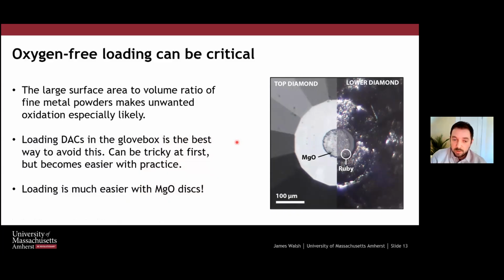The reason this is especially useful for us is if you're dealing with oxygen sensitive materials, such as finely ground metal powders, which can oxidize, and they more readily oxidize when they're fine powder because the surface area to volume ratio is higher. Then if you have to load in a glove box, being able to use magnesium oxide actually makes things a lot more straightforward. We typically will put one piece of the MgO sandwich in the gasket, the other piece on the opposing anvil, and then we close it up in the glove box after having dropped the sample into that space. So this is more technical detail than I would usually give in a chemistry talk.